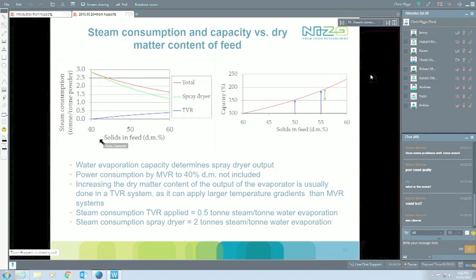Say, if I start varying my solids in the feed, increasing that bit by bit, my spray dryer steam consumption will start going down quite a bit, of course, because we have less and less water to evaporate. Of course, my evaporator will go up, but the overall balance is that it will keep going down. And since water evaporation really determines the capacity, the dryer output, my capacity of the dryer will increase a lot, even if I increase dry matter only by a few percent where possible.